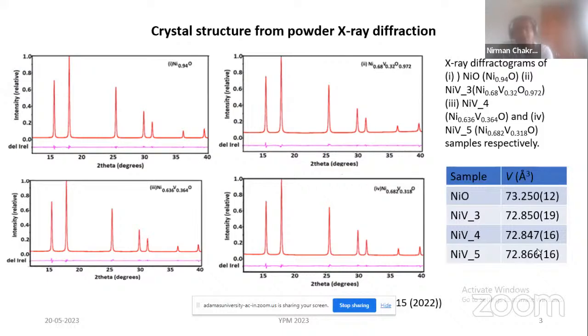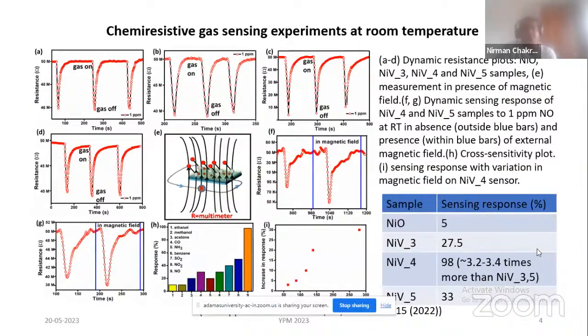Now we performed chemiresistive sensing experiments with our pure and doped systems. We found that while the pure system has a sensing response of 5% towards 1 ppm nitric oxide, which is a paramagnetic gas, the doped samples have nearly 4 times greater sensing response. One particular composition, NiV_4, has a 98% sensing response, which is nearly 3.2 to 3.4 times more sensitive than NiV_3 and NiV_5. These plots show the sensing response of the pure and the doped samples.